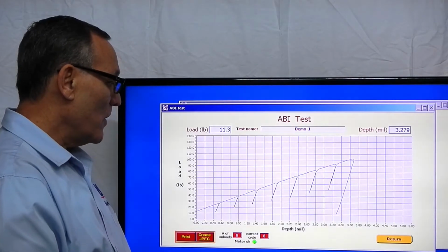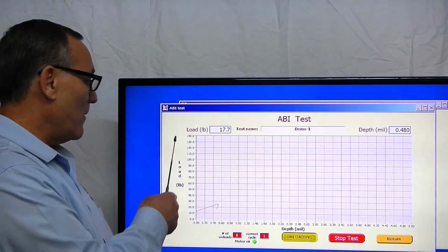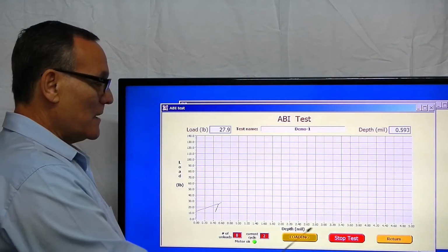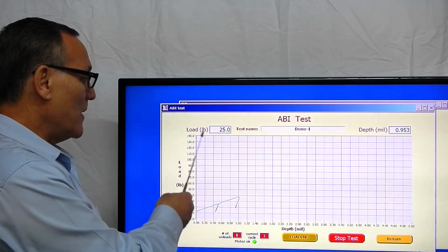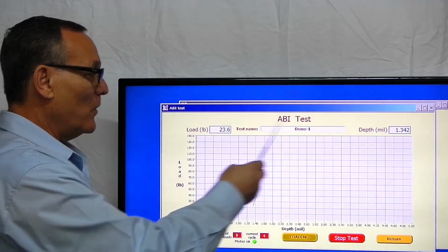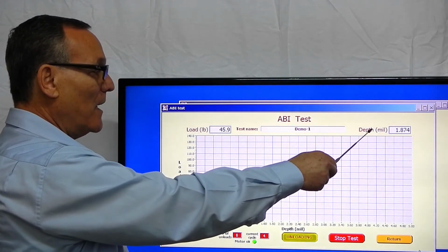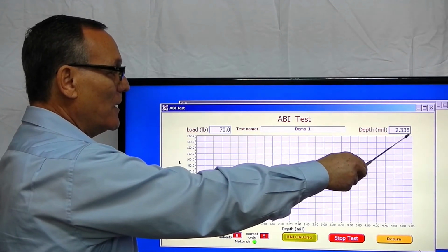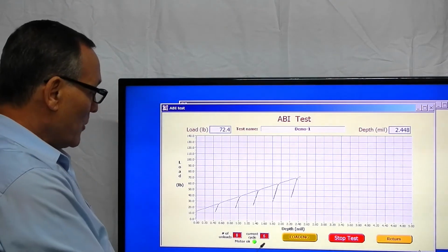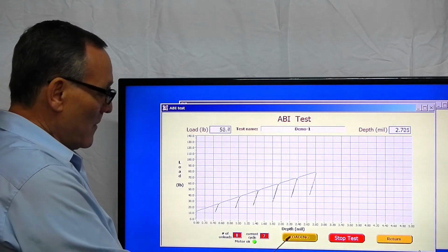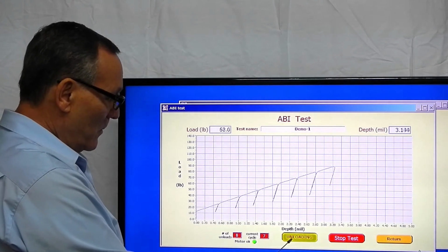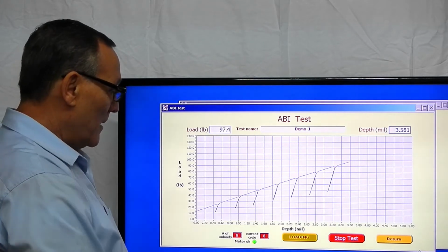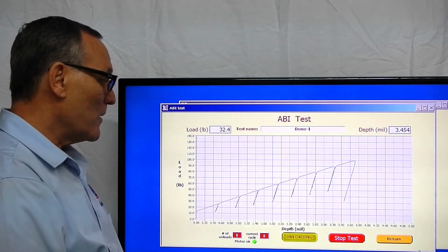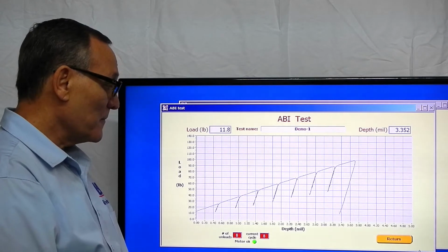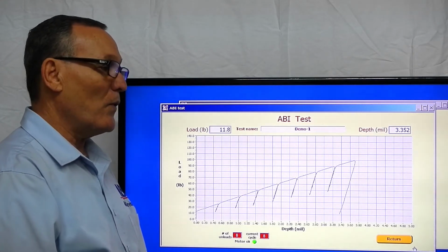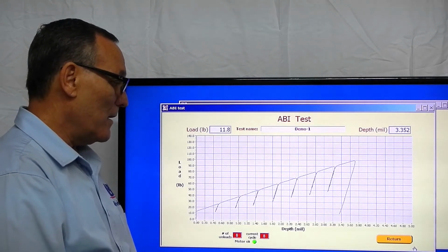We're going to continue. Now we're going into the real-time display of indentation load versus indentation depth. And these are digital displays of the actual value of the load and the actual value of the depth in mils, thousandths of an inch, and the third digit is millionths of an inch. And now it's showing the cycle number as it goes. Now it's loading and then goes to unloading. And now it's in cycle 8, where it's going to fully unload the indenter. And once the indenter is fully unloaded,